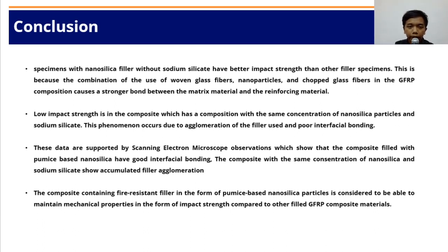Low impact strength is found in the composite which has a composition with the same concentration of nanosilica particles and sodium silicate. This phenomenon occurs due to the agglomeration of the filler used and poor interfacial bonding. These data are supported by the scanning electron microscope observation, which shows that the composite filled with nanofiller pumice particles has good interfacial bonding. The composite with the same concentration of nanosilica and sodium silicate shows accumulated filler agglomeration.